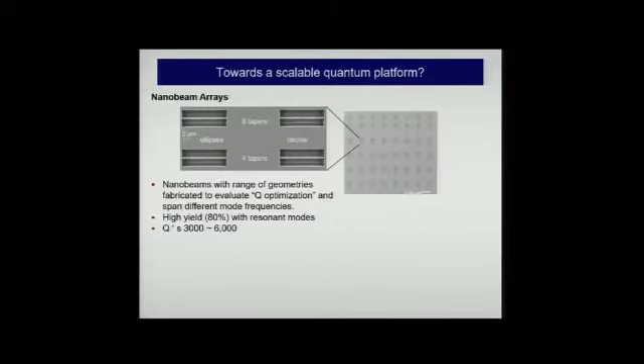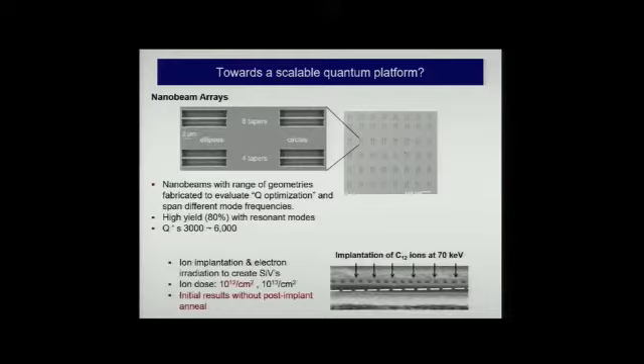This is just to show you that this technique, this idea of having a semiconductor platform, being able to use many of the planar techniques that we use in fabricating other kinds of devices, allows us to make arrays of thousands of these devices, with very reasonable yield for these nanobeams, with very good values of Q. After we fabricate the devices, we implant defects at a variety of different conditions. I'm going to show you results for implantation of carbon ions at 10 to the 12th ions per square centimeter.